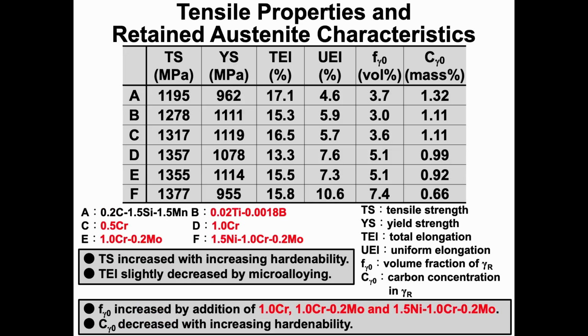This figure shows the tensile properties and retained austenite characteristics of the TBM steels. The tensile strength increased, whereas total elongation slightly decreased by the addition of alloying element. Volume fraction of retained austenite increased, and its carbon concentration decreased in the steels D, E, and F.